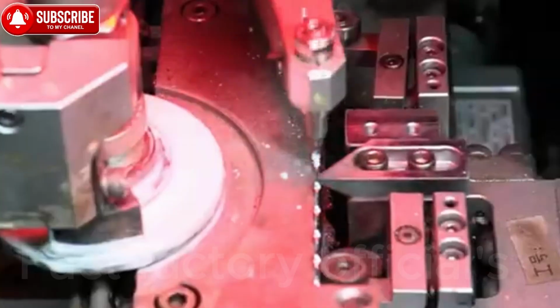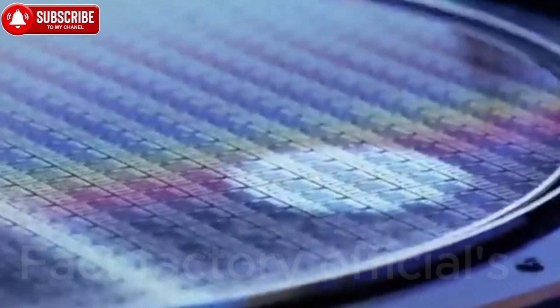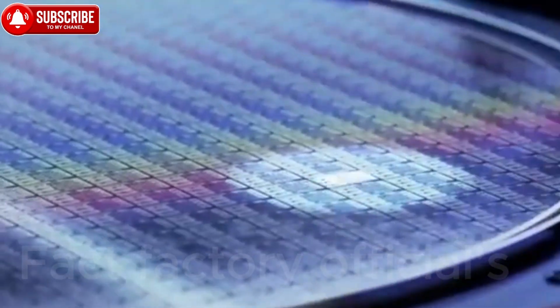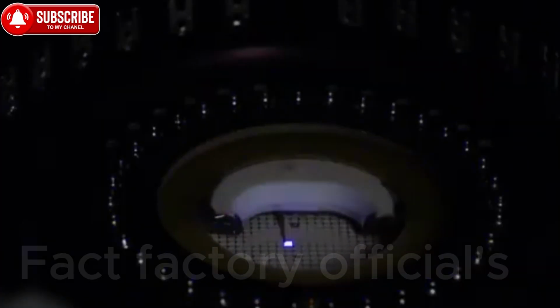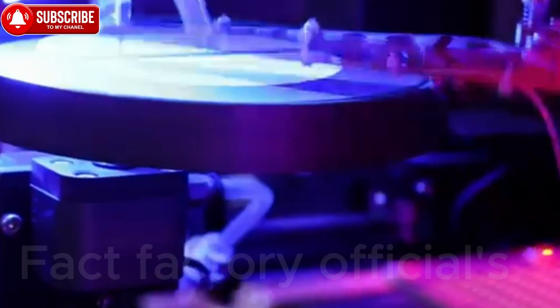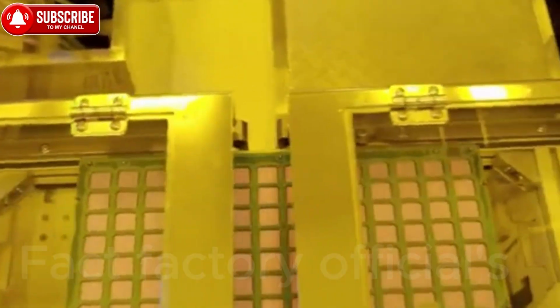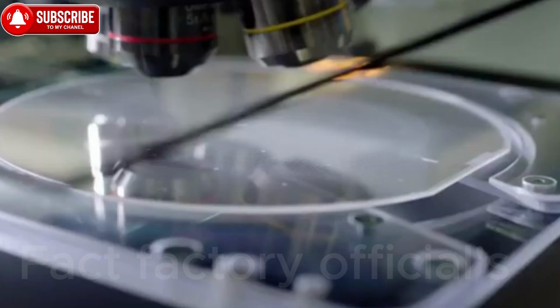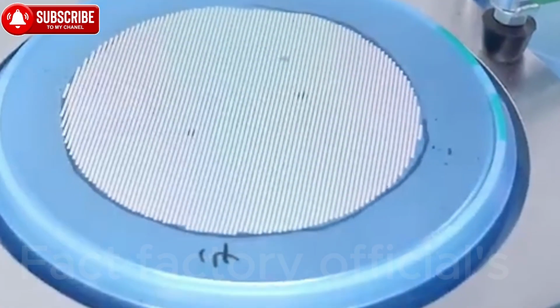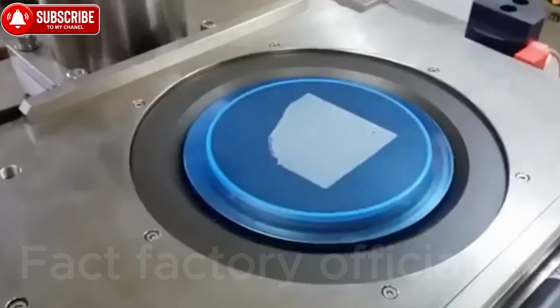After the wafer has been cut into thousands of tiny LED chips, all of them still remain firmly attached to a thin carrier film. In this state, robotic systems cannot pick up individual chips with micrometer level accuracy. For that reason, the film is fed into a crystal expander machine. Uniform tension is applied from all four directions, stretching the film outward. As the film expands, the chips gradually separate from one another, increasing the spacing between them according to pre-calculated dimensions. The result is a perfectly ordered chip grid, where every die is evenly spaced and precisely aligned.